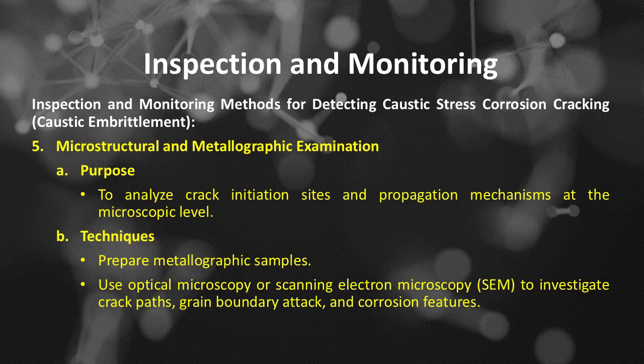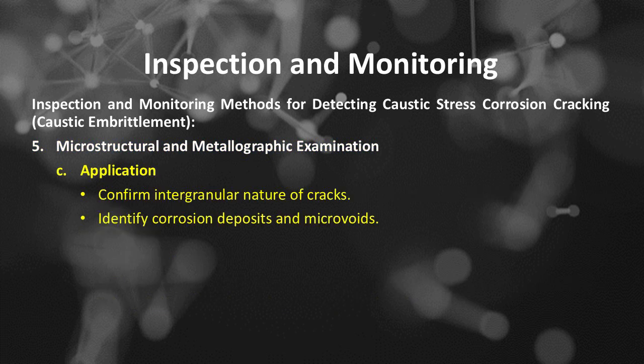Inspection and monitoring methods for detecting caustic embrittlement. Number 5 is microstructural and metallographic examination. It is purposed to analyze crack initiation sites and propagation mechanisms at the microscopic level. Microstructural and metallographic technique procedures: prepare metallographic samples, use optical microscopy or scanning electron microscopy, SEM, to investigate crack paths, grain boundary attack, and corrosion features. This examination is applied to confirm the intergranular nature of cracks and to identify corrosion deposits and microvoids.